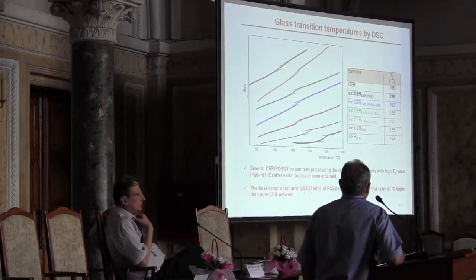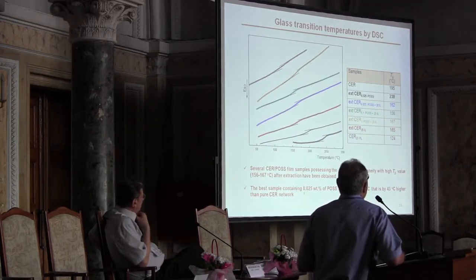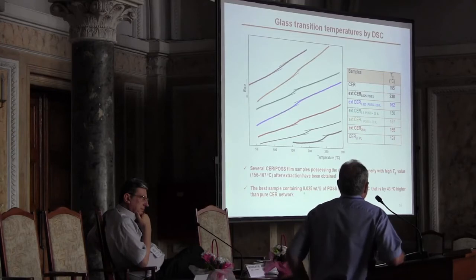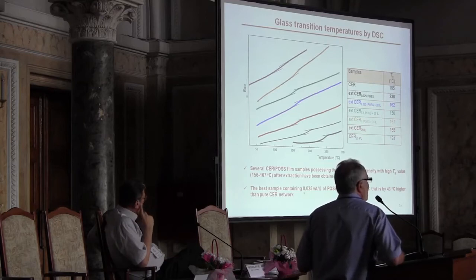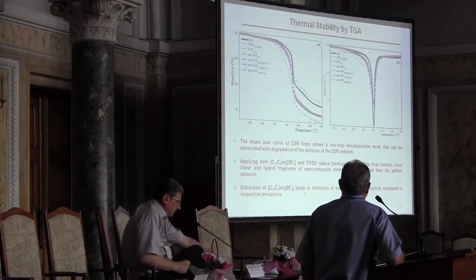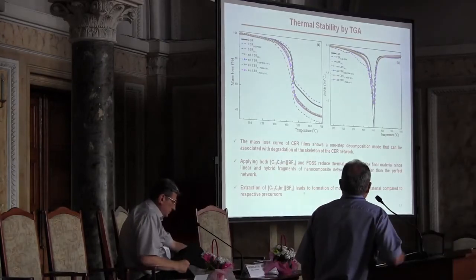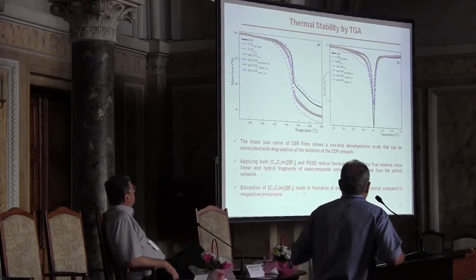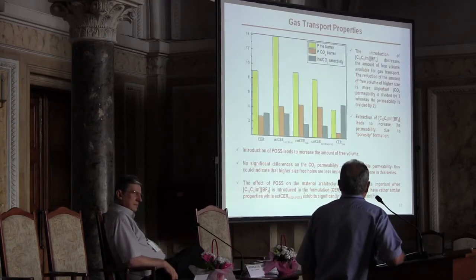CER network with 0.025 weight percent of POSS, a very low amount of this nanofiller, led to the formation of a network with a glass transition temperature even higher than the pure regular structure polycyanurate network. Also high thermal stability, around 400 degrees centigrade.